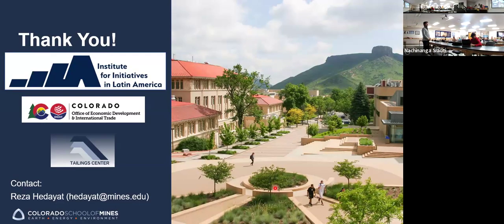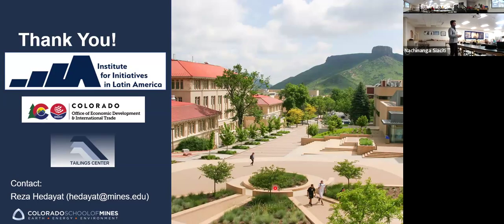Yes, correct. The tailings that we collected from the La Libertad region, in the north of Peru, some of those had high sulfur content. So we had this challenge. I think in some cases they even had 20% of the element sulfur in those tailings. We used them for ceramic production, but that required us to go through a calcining step where you need to expose the tailings to 700 degrees Celsius to try to burn off the sulfur. You probably cannot fully get rid of it. And I would imagine that this is not a very environmentally safe process, because you still have hazardous gases that get emitted. So while it was successful at the laboratory scale, I do believe that additional processes need to be in place to be able to reduce the sulfate content for these samples.